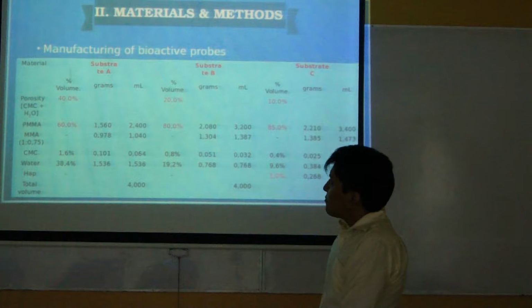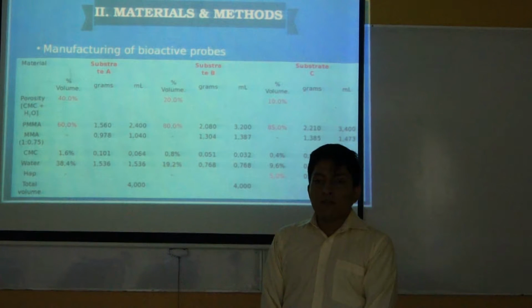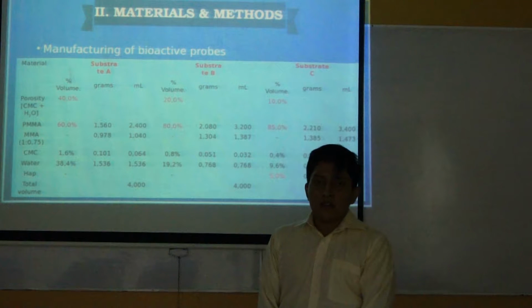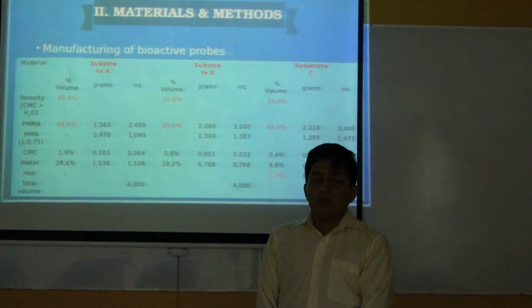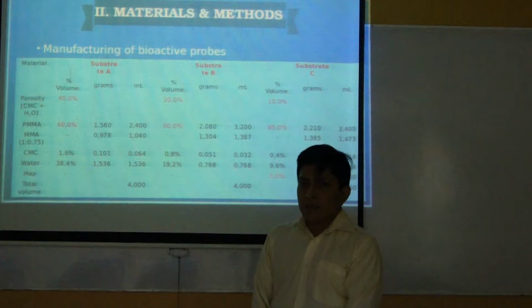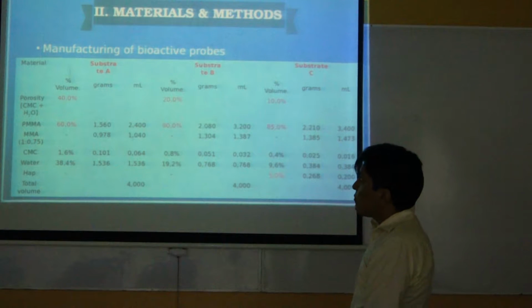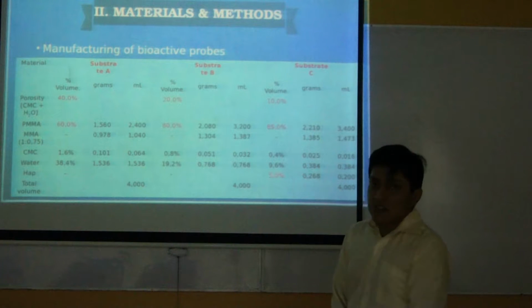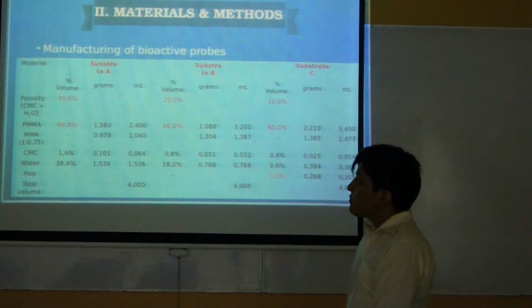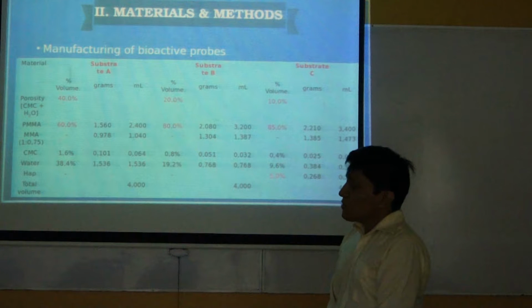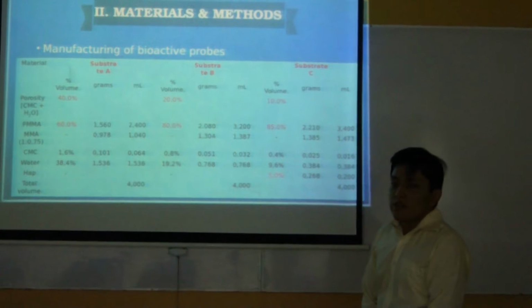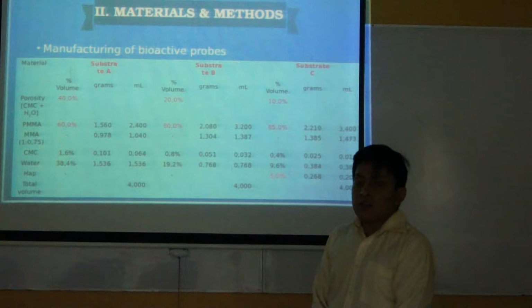Bioactive probes of 5 mm diameter and 3 mm thickness were made. Each probe was duplicated 5 times. They were made with PMMA in the form of bone cement. Here we have a chart where we can see the first 3 compositions. The first one contains 40% porosity with CMC gel, the second one 20% porosity, and the third one 10% porosity with 5% hydroxyapatite.